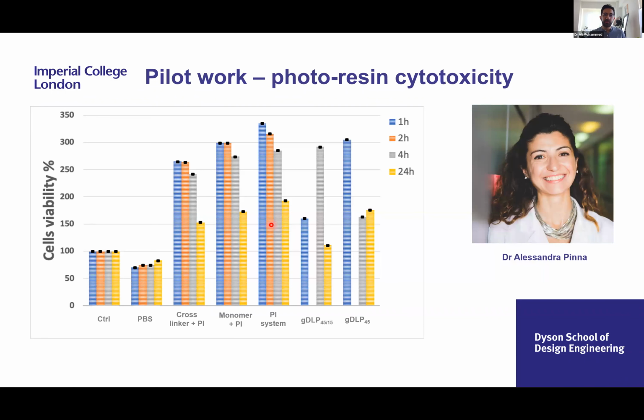So next, part of the pilot work was to look at the photoresin cytotoxicity. Dr. Alessandra Pinna was kind enough to do the cytotoxicity studies on the photoresin, and this used ATDC5 chondrocyte cells. They are derived from mouse teratocarcinoma cells. Alessandra allowed the cells to attach to the flask for 24 hours before testing them with our cross-linker and the photoinitiator system, the monomer with the photoinitiator system on its own, and the two various resins that we developed.